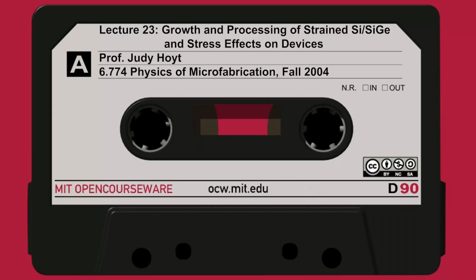So now the other thing, that's if it's strained. If it's unstrained, if you grow the silicon germanium so thick that it relaxes back, so it comes back to be this cubic structure, then what happens to the band gap? Well, in fact, the band gap difference is a lot smaller. When it's unstrained, the band gap difference, say at 20%, is only about 100 millivolts. So a big fraction of this band gap offset, this band gap difference, is due to the strain. It's due to the lattice parameter change. A certain fraction is due to the fact that we're just adding germanium. So you need to know whether the material is unstrained or strained or somewhere in between in order to figure out what the band structure looks like.